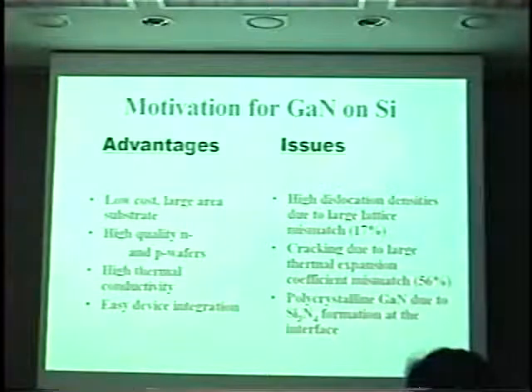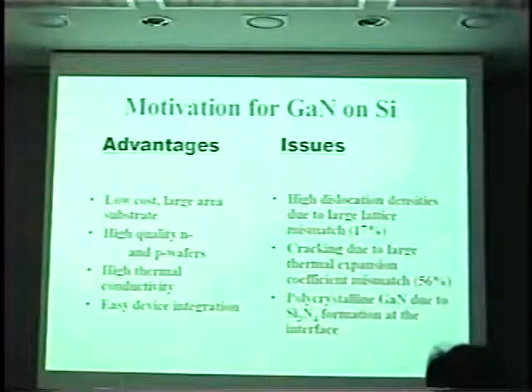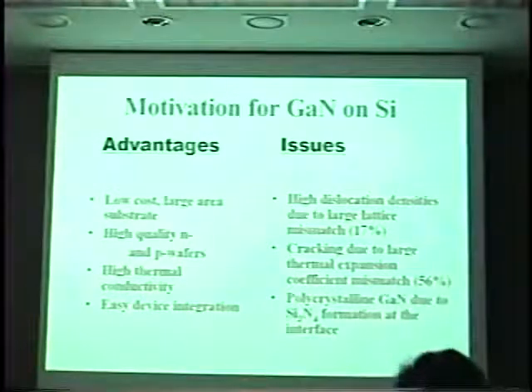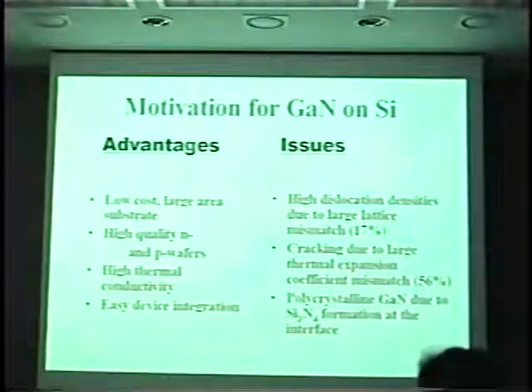However, it does have an extremely large lattice mismatch, 17%. The thermal expansion coefficient is different as well by quite a bit, 56%. So the relatively high temperature growth of gallium nitride, on the order of about 1050 degrees C, produces a large strain, which can then deteriorate the quality of the gallium nitride. Also, people have not had very good luck growing gallium nitride. Gallium nitride will not grow on SiO2. If you remove the oxide and start your growth using ammonia as your precursor, you'll quickly form a silicon nitride, which again prevents high quality growth on silicon.